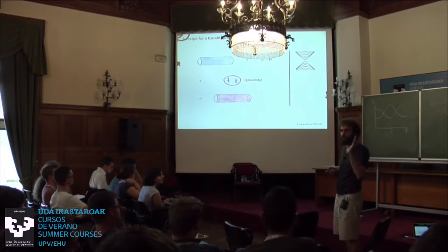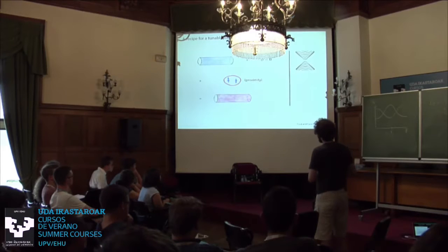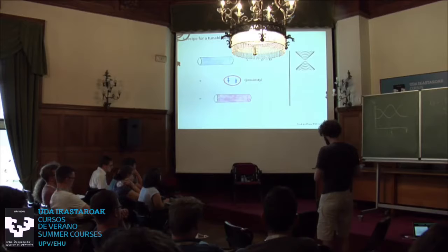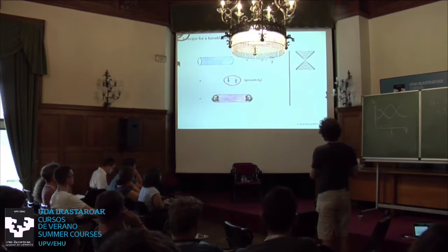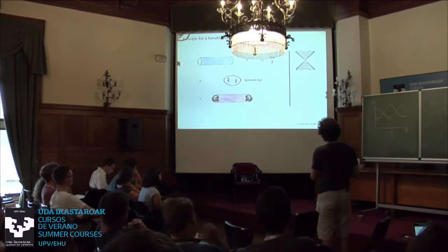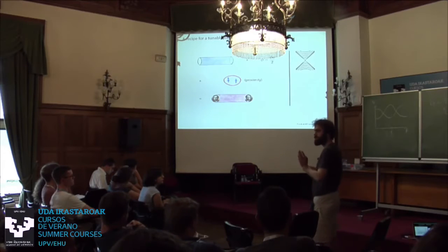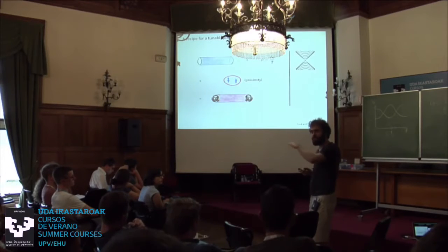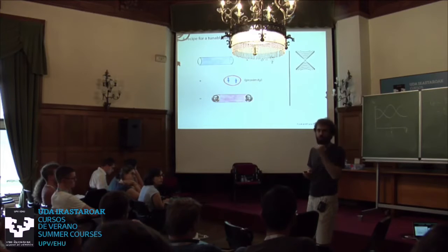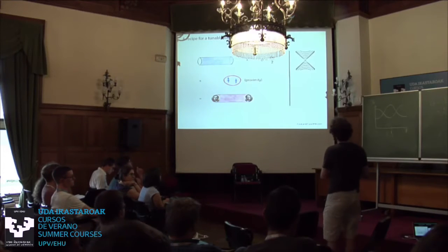It's a boring superconductor that is gapped. And the reason it's boring is just that I have these parabolic bands, nothing interesting happens. But if instead of having flux 0, I have flux pi, then I have this odd number of modes and a Majorana appears at the end. So it's easy to understand if we ignore all the higher modes and we only look at this lowest mode, which is linearly dispersing. That's essentially like the Kitaev chain, because it's now a 1D mode, and you can map this basically onto the Kitaev chain.